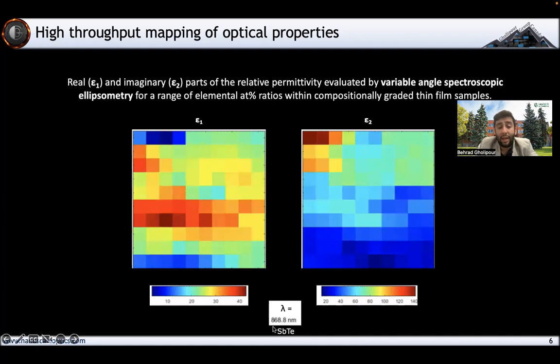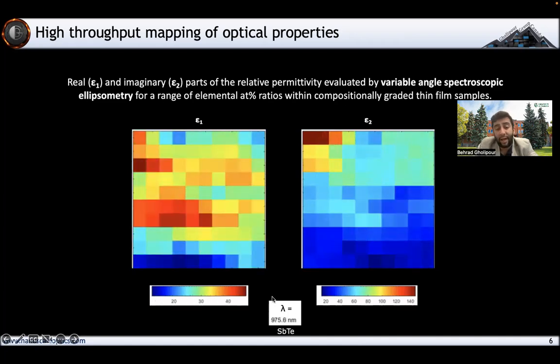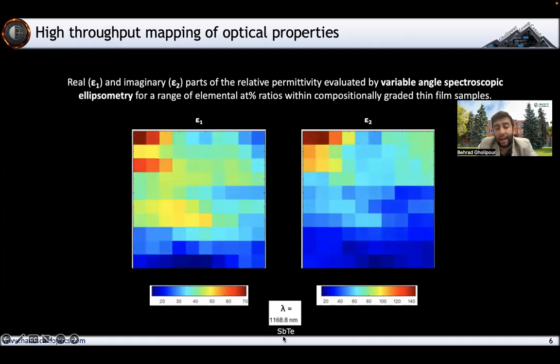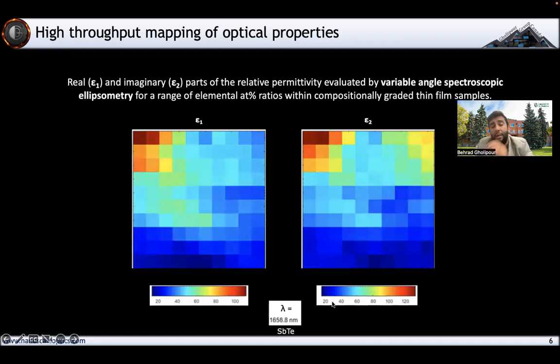And what I'm showing you here is the real and imaginary part, and we're cycling through the wavelength here, as you can see. I've just picked a random alloy, and we've done many different alloys over the years. Antimony telluride here is one alloy that we're quite interested in. It has a lot of good switching capability, but also has some interesting functionality for photovoltaics, which we're looking at.